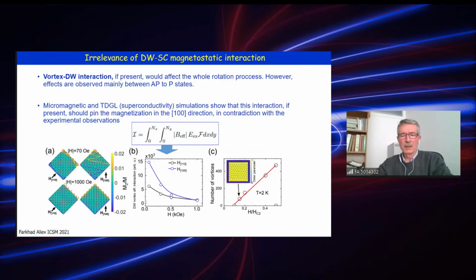We analyzed numerically also possible vortex domain wall interaction by calculating stray fields which affect the superconductor, by mapping the vortices in the superconductor and calculating the interaction energy between these stray fields and domain walls. Our conclusion was that if there is any interaction, it will be stronger for interaction along the easy axis, but not along the hard axis.